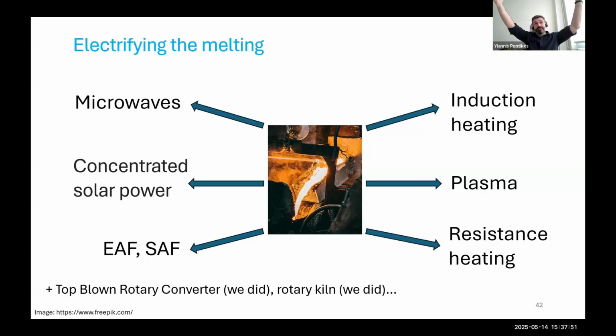So imagine you have these mirrors, eventually having the solar light concentrated on a very, very thin beam that has very high temperature, and you have a conveyor belt with your material passing and you melt it in real time. We've done EAF, and submerged arc furnace is an option we haven't done. Plasma, we're now thinking of going into that, but we've done a plasma reactor in Sweden, and resistance heating, that's how things get started. And of course, you can also do resistance heating on a big scale. You can see foundries, and that's what they often use. We've also done top-blown rotary converter, TBRC, and we also did a rotary kiln that you will see in a slide.